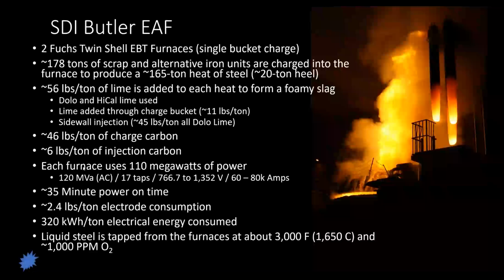We're running our furnaces at about 110 megawatts. We have 120 MVA AC transformers, and 17 secondary voltage taps. We run between 766 and 1350 volts, which means we end up somewhere between, generally on average, 60 to 80,000 amps at any given time.